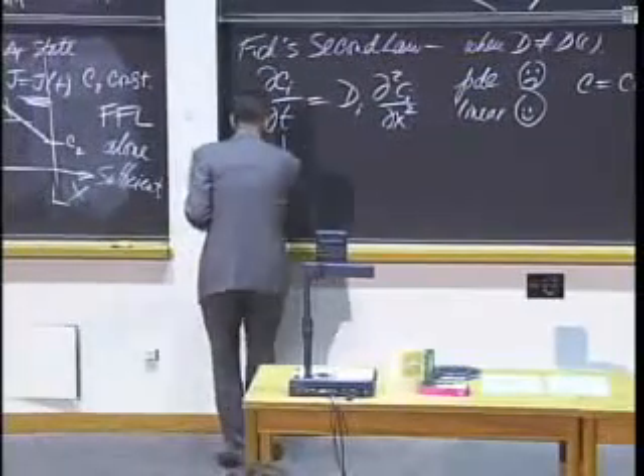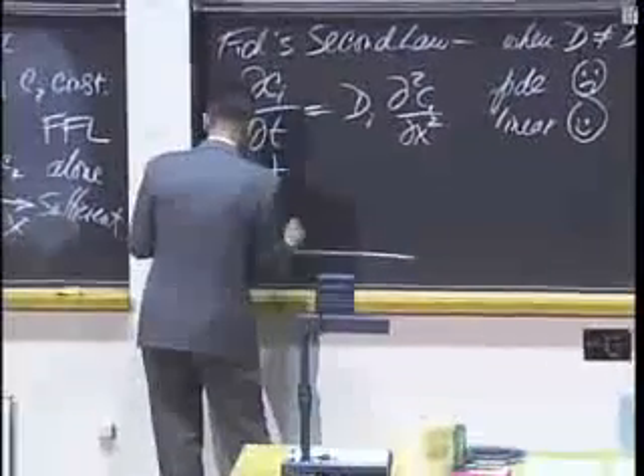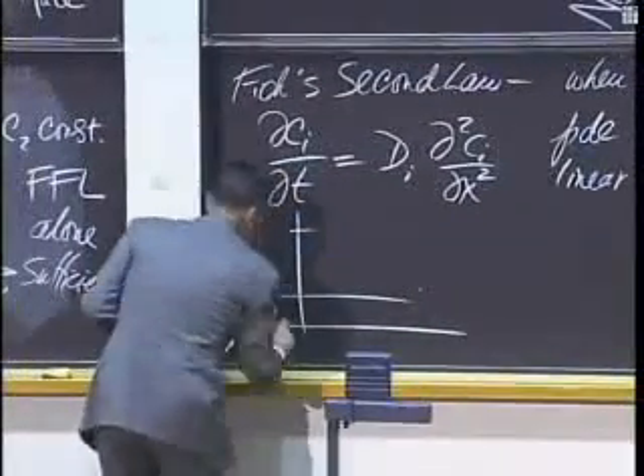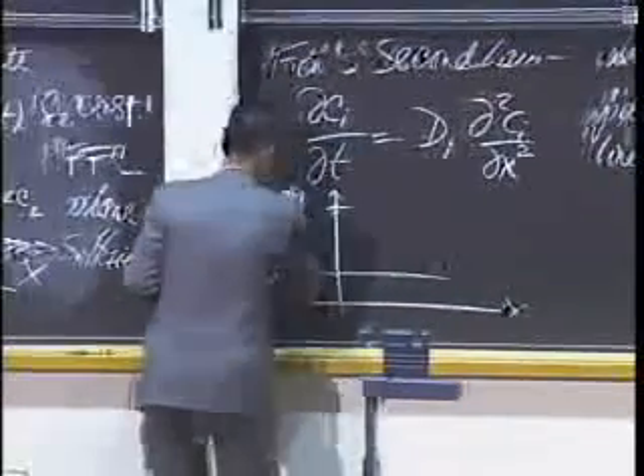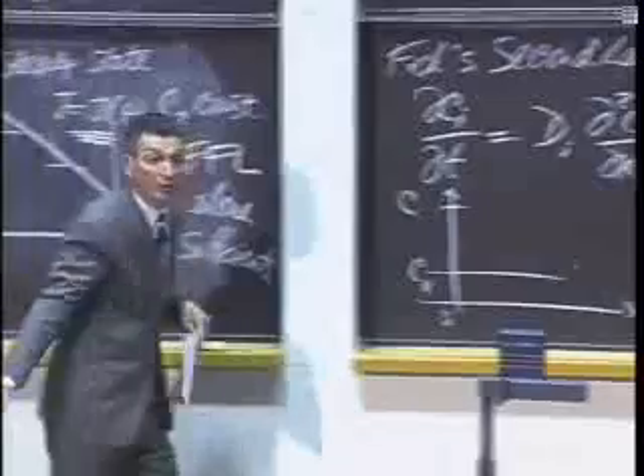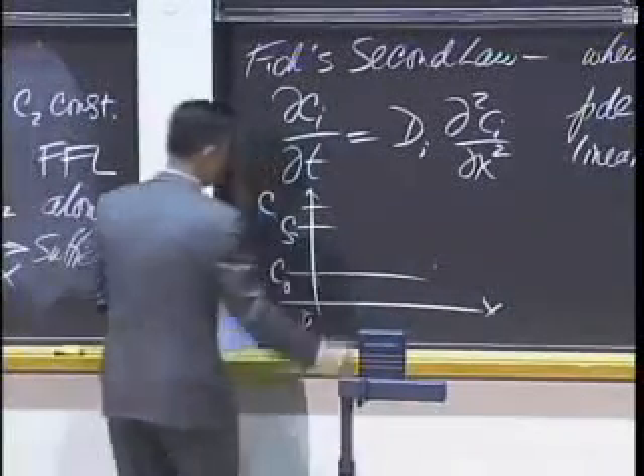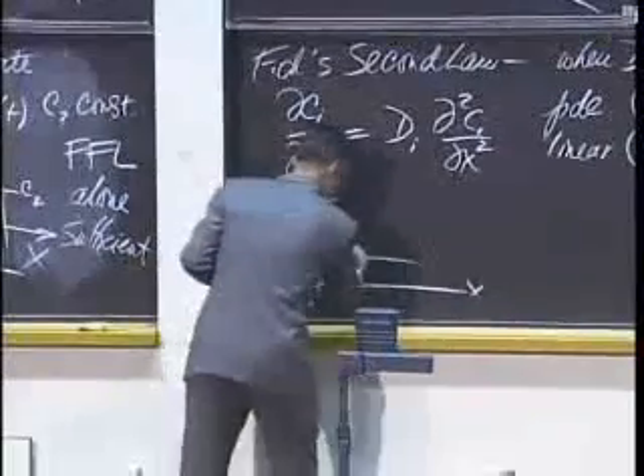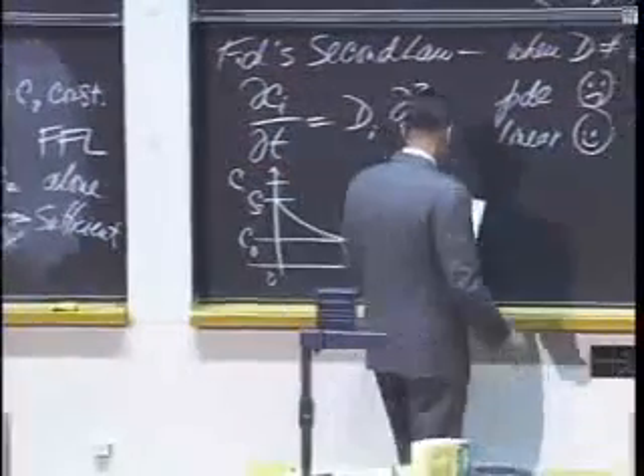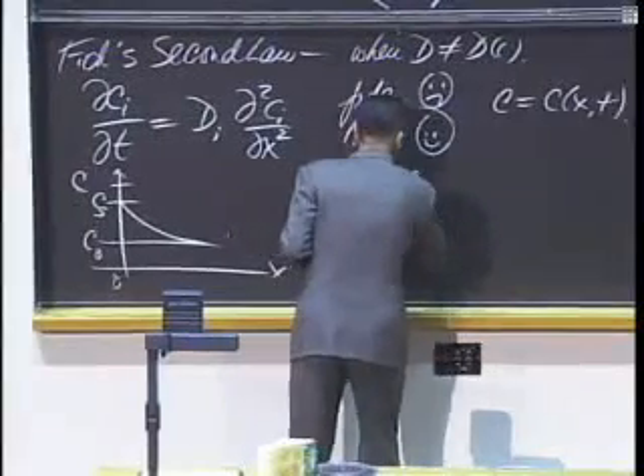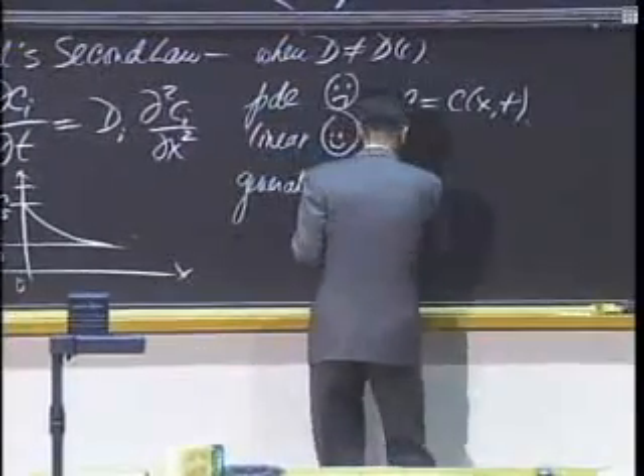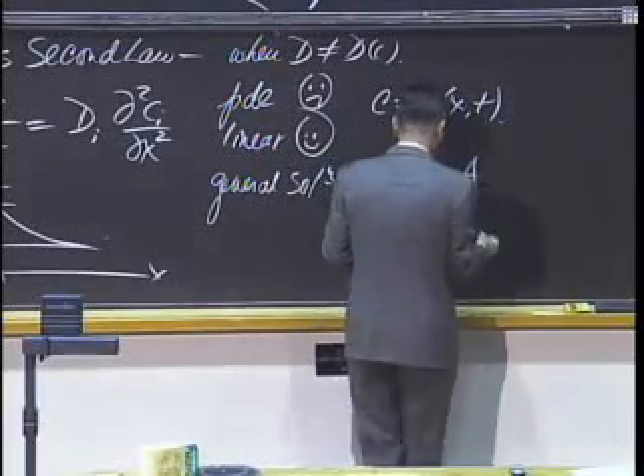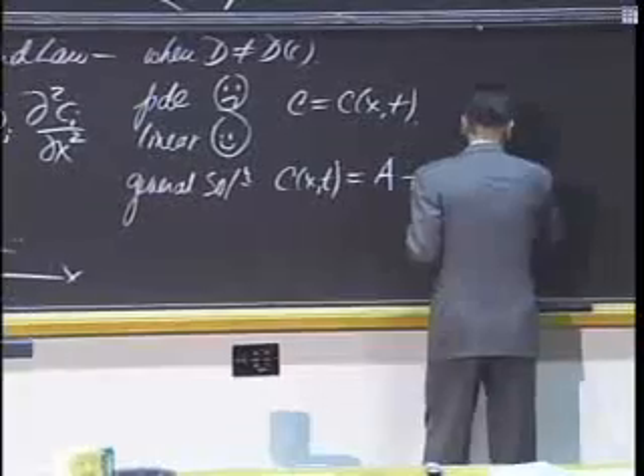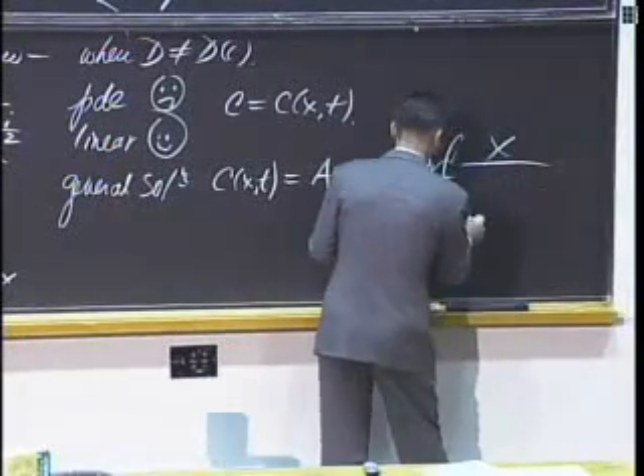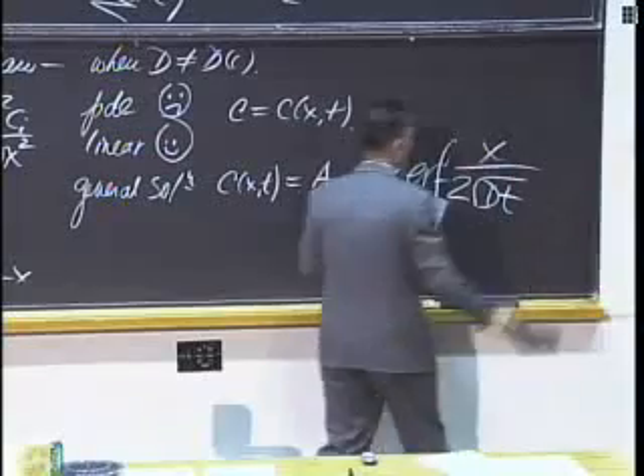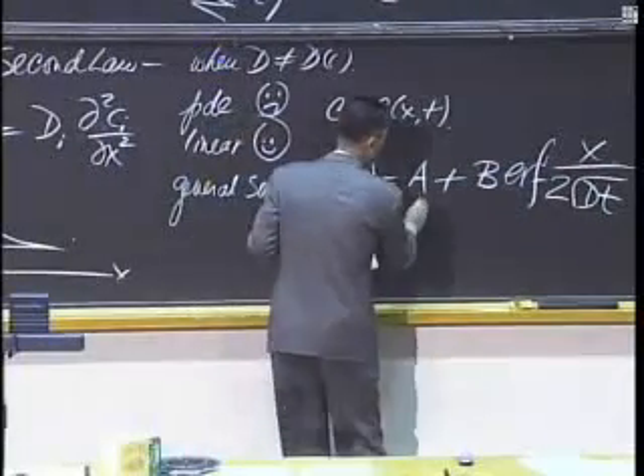And the solution looks like this. Let's say we have an initial concentration C naught. C is a function of X. So I have an initial non-zero concentration C naught, and I have a surface concentration fixed at Cs, and this is the system that we're trying to model. And the general solution to Fick's second law is C of X and T is some constant A plus a constant B times a function, which I'm going to define for you in a second, the Gaussian error function of x divided by square root of Dt. So these are both constants to be determined.